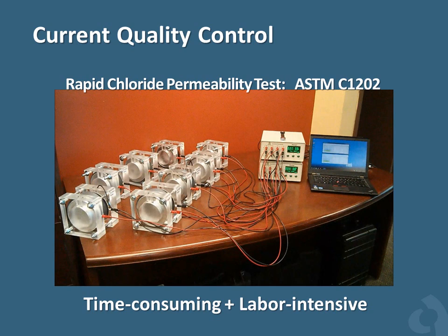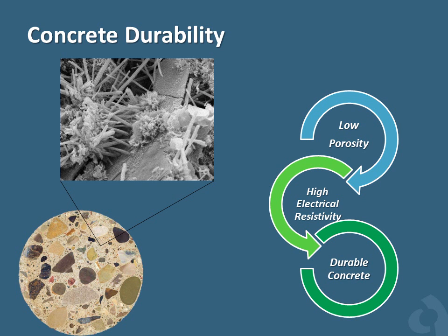The test preparation and setup is labor-intensive and very time-consuming. Concrete is a porous material, and the durability of concrete depends largely on the properties of its microstructure, such as the pore network size and interconnections. A finer pore network with fewer connectivity leads to lower permeability. A porous microstructure with a larger degree of interconnections, on the other hand, results in higher permeability and reduced durability in general.